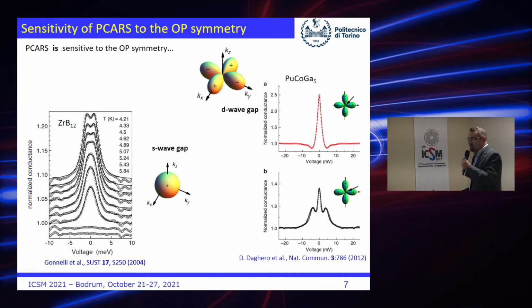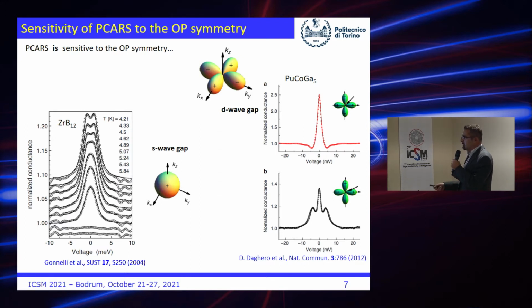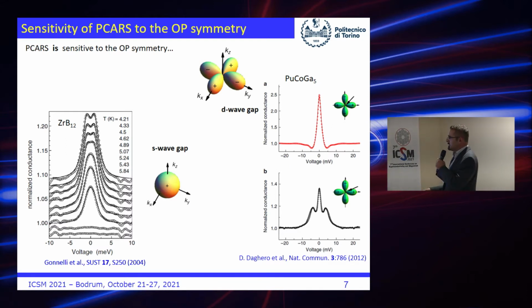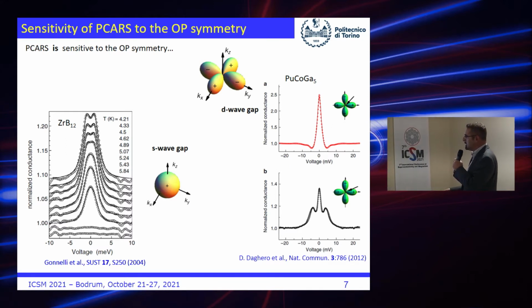These slides are just made here to show that point contact spectroscopy is sensitive to the symmetry of the order parameter. These are spectra in an S-wave gap superconductor, so this is zirconium boron 12, and these are spectra taken in plutonium cobalt gallium 5, which is instead a D-wave superconductor. You clearly see that they are completely different, and this is due to the fact that in this case, depending on the angle with which you inject the current with respect to the lobes of the D-wave gap, you can obtain different kinds of spectra.